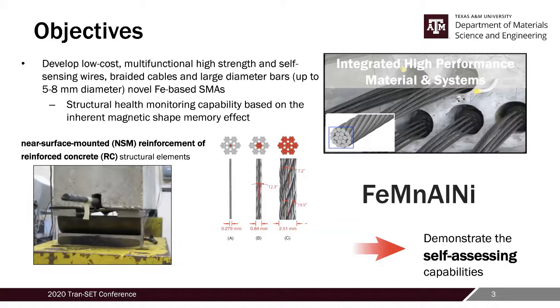Like I said, what we want to do is to develop low-cost, multifunctional, high-strength, and self-sensing wires, braided cables, and large diameter bars, because in structural applications, most of the time, common materials are cables or large diameter rods. So we want to scale up iron-based SMAs. And like I said, we want to demonstrate the self-assessing capability of iron SMAs using this magnetization change. And in conventional nickel titanium, again, you cannot get this magnetization change, and therefore that is not suitable for structural health monitoring applications.